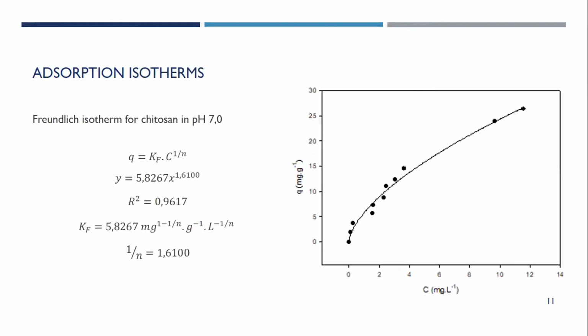Moving on to the adsorption isotherms. First, we have the Freundlich isotherm for Chitosan at a pH value of 7. The curve was built on a nonlinear regression which follows the equation shown. For Chitosan at pH 7, the Freundlich constant was 5.8267, while the exponent 1 over n, which represents the adsorbent's heterogeneity, was shown to be 1.61.